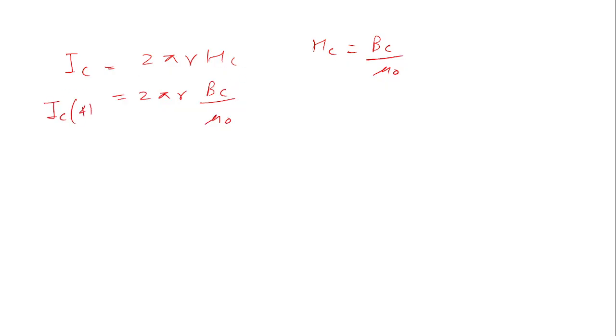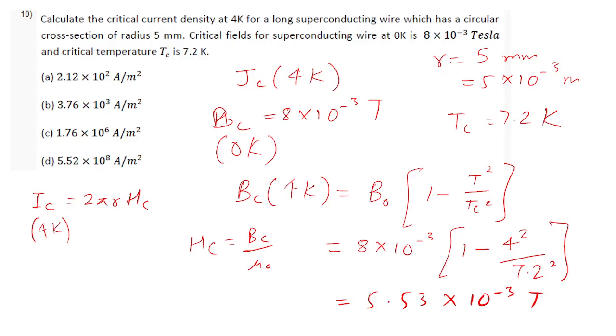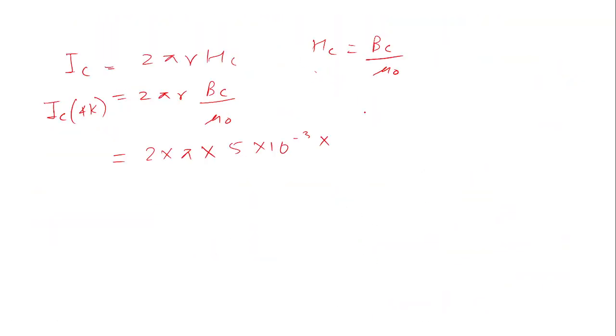So IC will be 2 pi r, and HC, as I told, will be BC divided by mu naught. This will be 2 pi r BC divided by mu naught. Now this HC and BC are at 4 Kelvin, so that I get IC at 4 Kelvin. This is not multiplication, I am just telling IC at 4 Kelvin. So this will be 2 times pi times r, which is 5 millimeter, that means 5 times 10 to the power minus 3, and BC I got 5.53 times 10 to the power minus 3, and mu naught is 4 pi times 10 to the power minus 7. When I calculate this, I will get